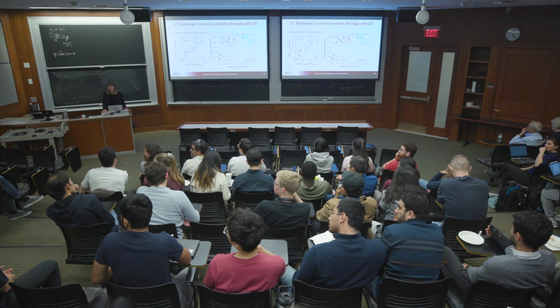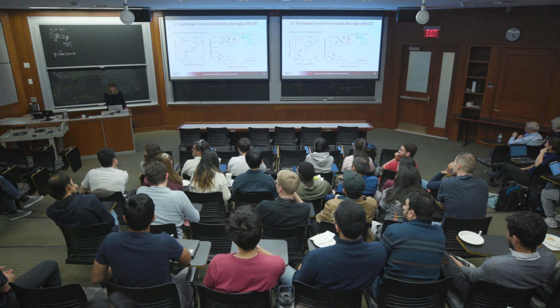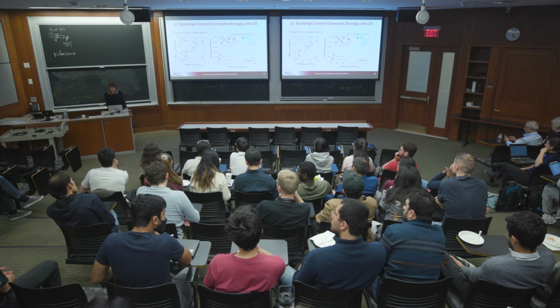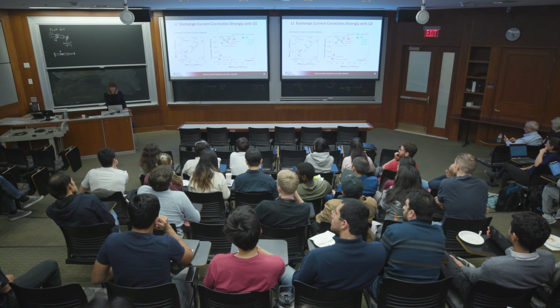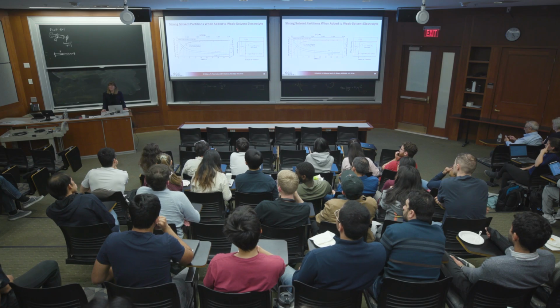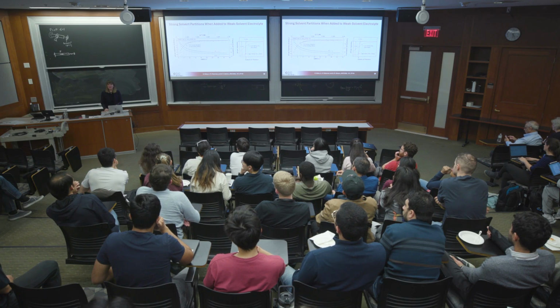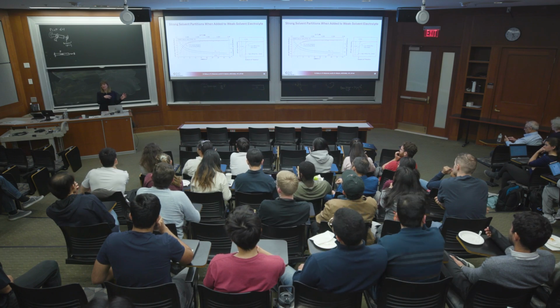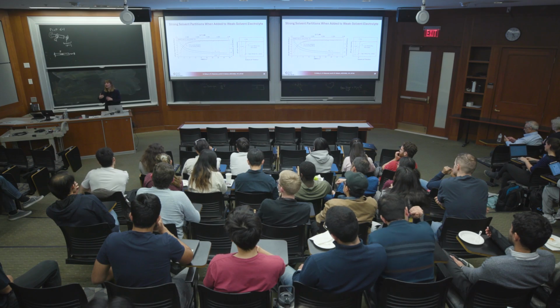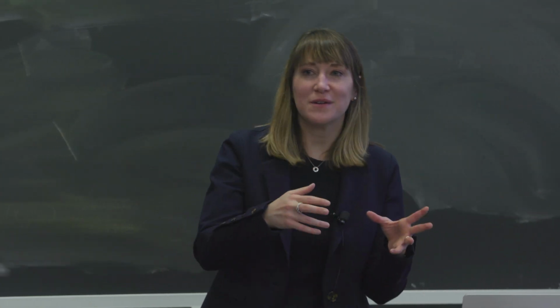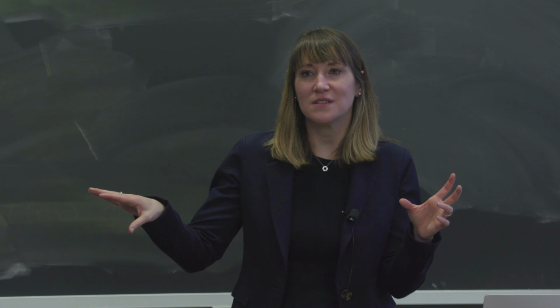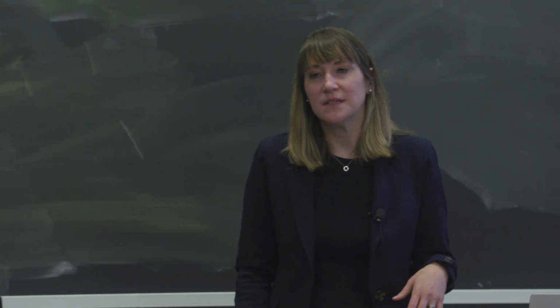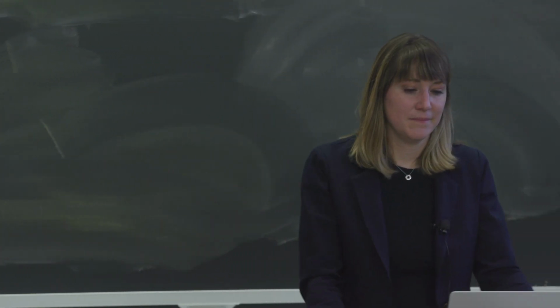And for slide 28, for the concentration of 0.1 molar, is it true that we don't see ion coupling there? Yes, we have validated that. In fact, that was essential to our analysis because in our later description in the binding model, we didn't at the time know how to account for ion pairing. So we check Raman spectroscopy. We make sure that there's negligible anion coordination throughout the entirety of the titration. Thank you so much.